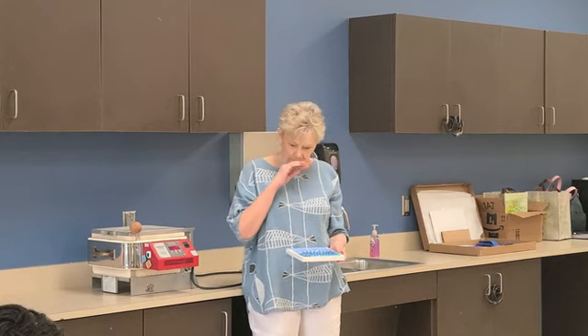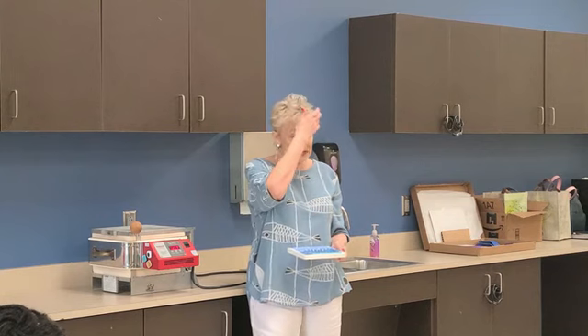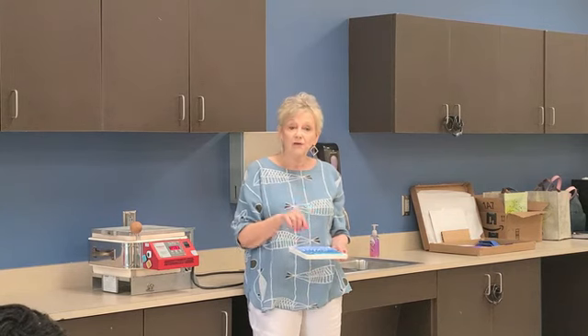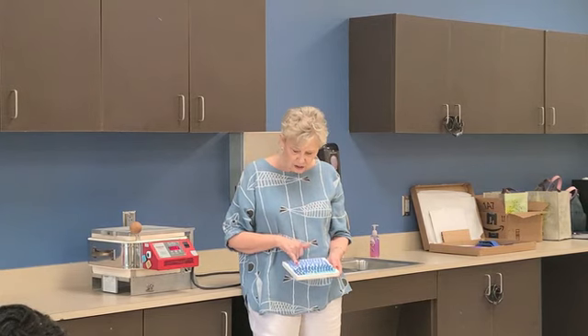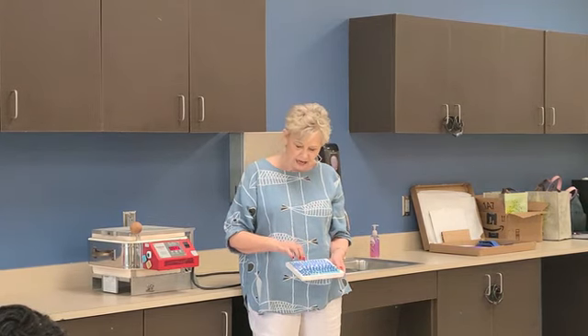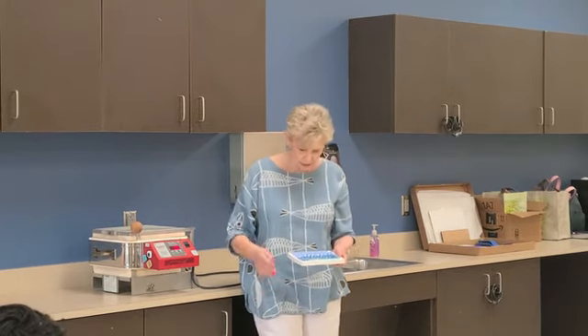If you have one layer of glass like this that's an eighth of an inch thick, then it's gonna pretty much double. If you have two layers of glass like here where I have these two, then they should round out to about that size into a sort of a dot, because they're not exactly square. I wasn't real meticulous, like I said. That's why I'm not a stained glass artist.